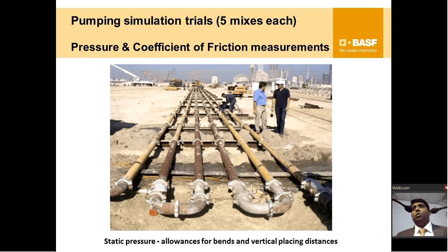Simulation tests were also done because you need to pump it to such a height. Simulation tests with five mixes each, measuring pressure and coefficient of friction, were done. So you pump the concrete through, and every bend is considered, which gives you a certain height. They had about 3 bends on that side and 2 bends on this side, which is equivalent to something like 600 meters, pumping to 600 meters tall.